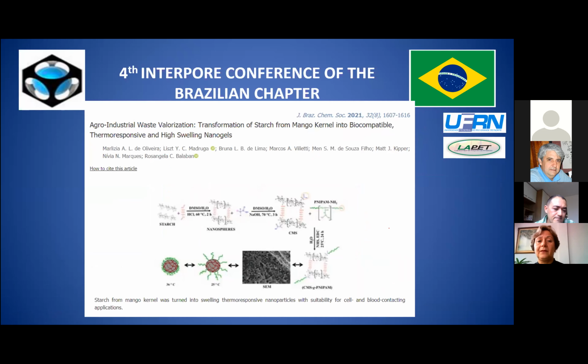In this work, we used starch from mango kernel to produce nanogels. So the starch was cross-linked with glutaraldehyde, and afterwards they were functionalized through carboxymethylation. And poly-N-isopropylacrylamide were attached to the surface of the nanogels through the reaction between the amine group and carboxylic group.